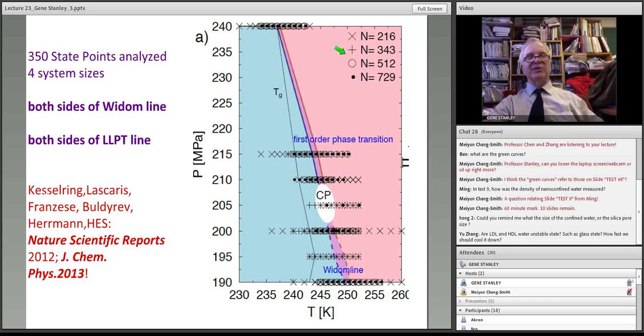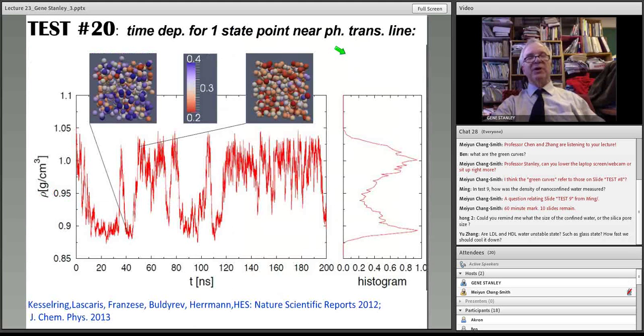So let's look at it as a function of time when we pick one state point, not all these points, there's 350 little marks here, but only one of them, reasonably near the critical point, and we watch as a function of time. This is the last and final test, number 20, and here's the density of the system as a function of time in nanoseconds. So there's a very long simulation, 200 nanoseconds. In the old days, when this started, you'd be lucky to get 200 picoseconds. So this is 1,000 times longer. And what do you see here?